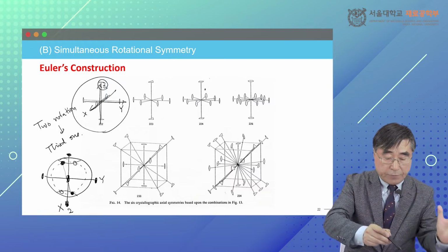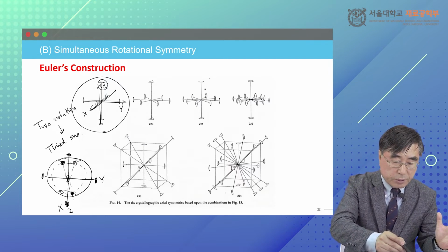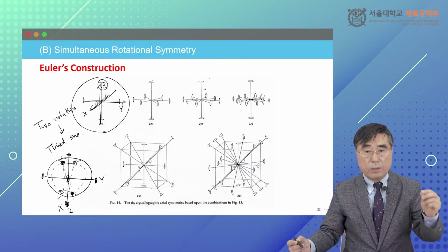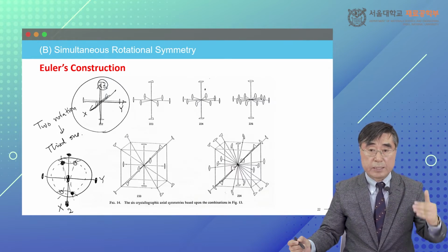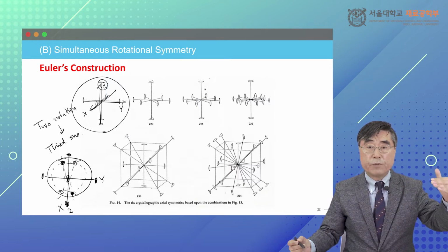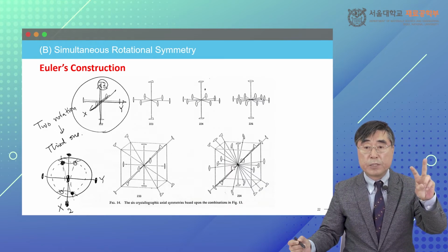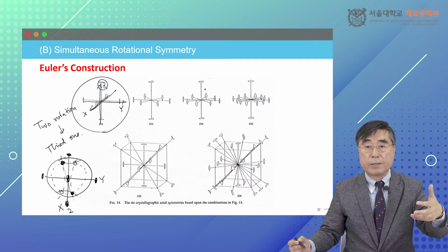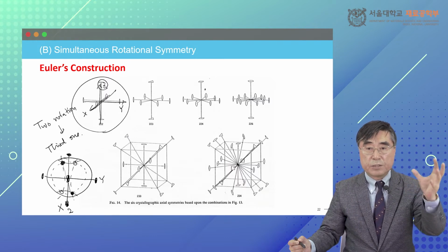But if you look at this Y-axis operation, you know it is already satisfied here. The third axis should be there, perpendicular to the X-axis and Y-axis, and it should have twofold rotational symmetry. It's just there. It does not generate any new poles. By just two rotation operations, the third operation is already there. It does not generate any new poles. So this is what I meant: for multiple rotation axes, the three axes should be defined with certain symmetries.